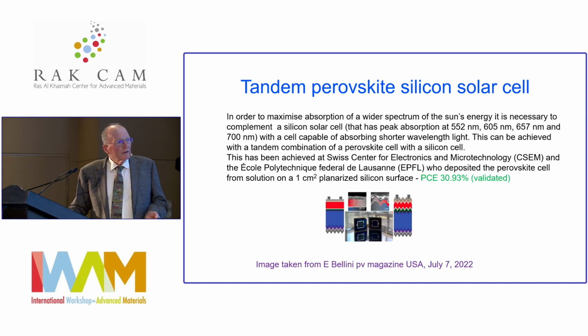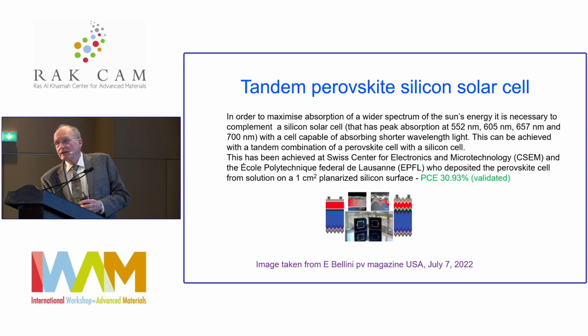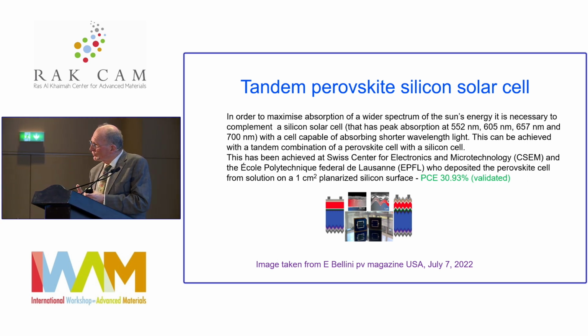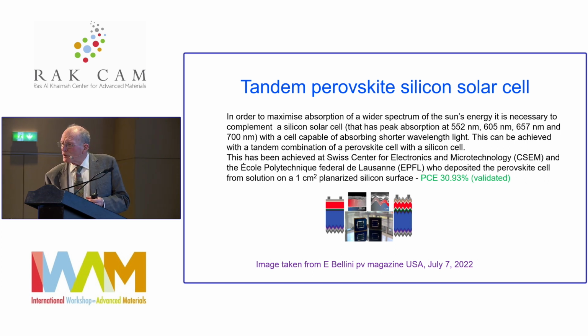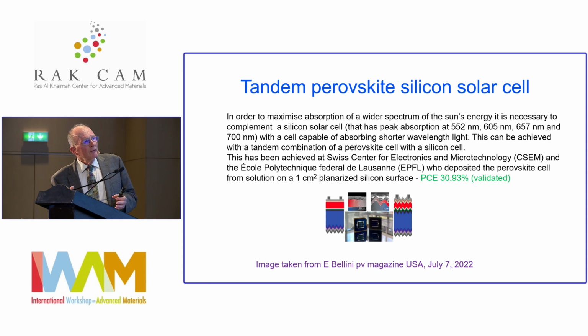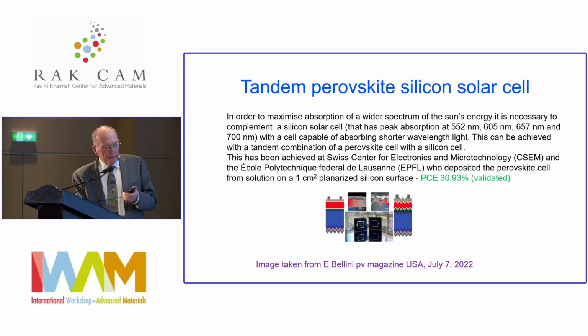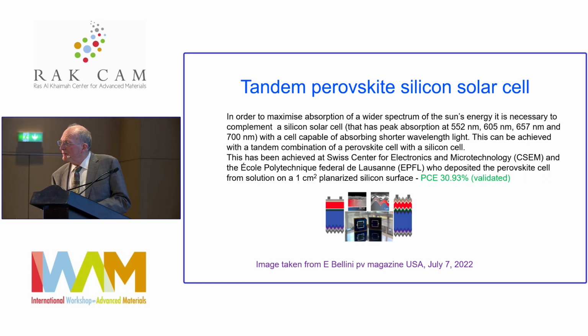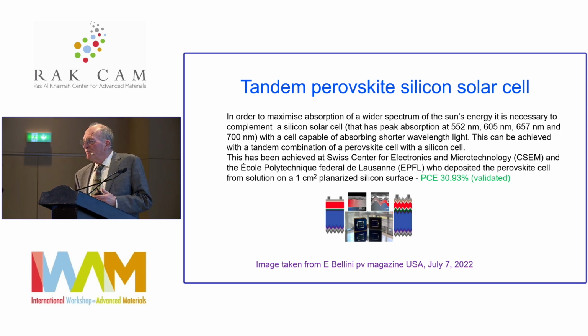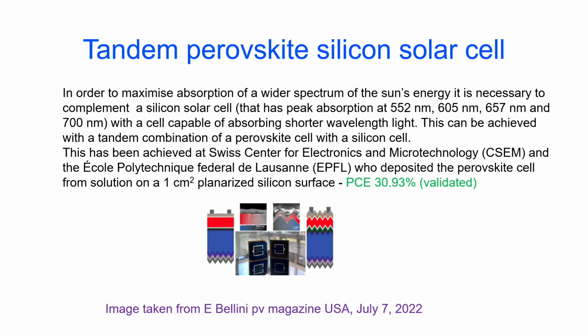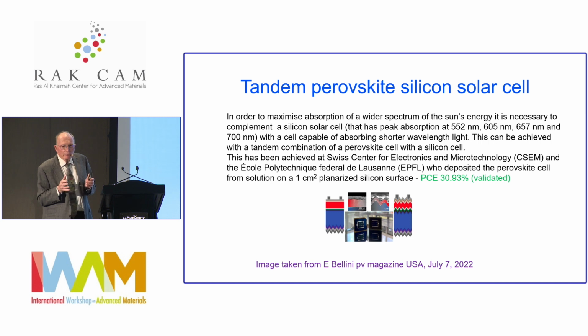What else has been done? Well, I'd like to talk here about tandem solar cells for a minute. Now, this is used in sophisticated silicon solar cell science as well, but as described on the slide, silicon absorbs quite long wavelength regions of the solar spectrum, around the 650 and 700 being the main absorption. There are other absorptions. But the idea is that anything that is excited with a shorter wavelength excites the excitonic state in silicon beyond the level where charge separation can occur, so it's lost as heat. And so the idea, which is well developed in this area, is to have in front of the silicon cell a solar cell capable of absorbing the short wavelength light, and then to couple these in tandem to get more energy from the solar spectrum.